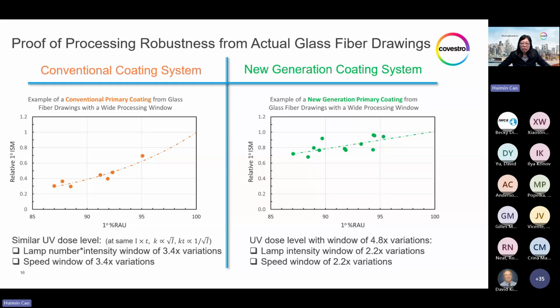Although our study was using a draw tower simulator, it is intended only to be a simulation tool. In the end, the ultimate proof of processing robustness needs to come from the actual fiber drawing process. And these slides compare 2 glass fiber drawing trials that were intentionally set with very wide processing windows. On the left, with the conventional coating system, on the right with the new generation coating system.